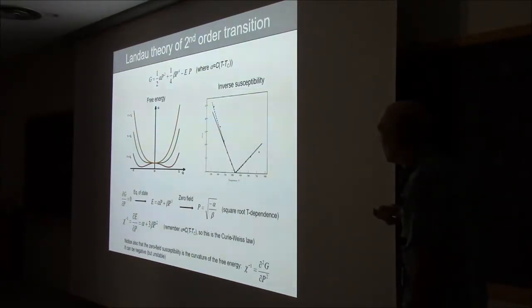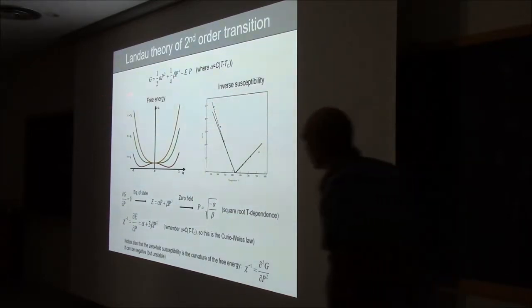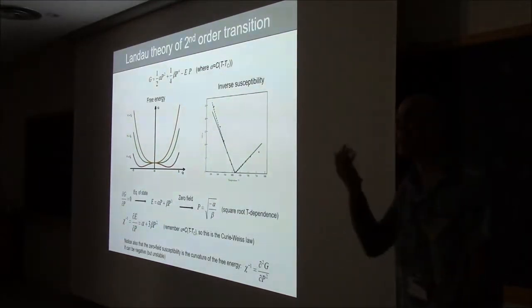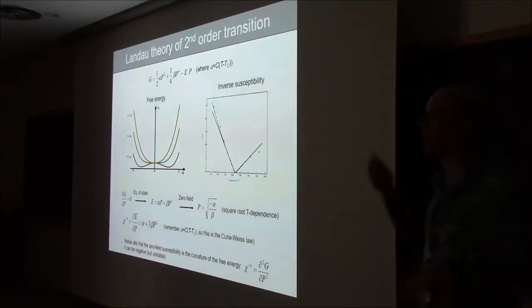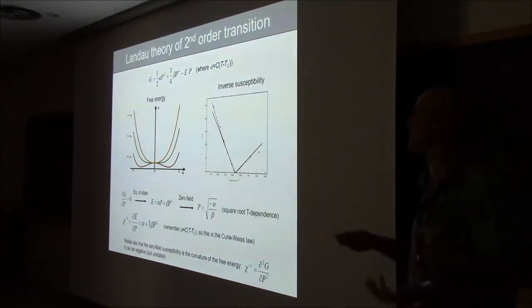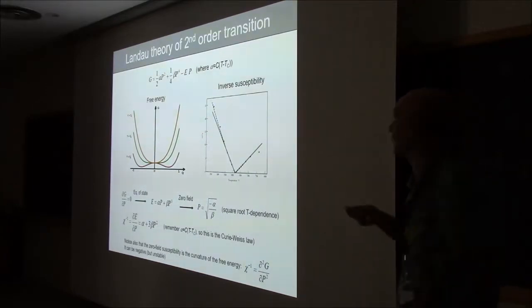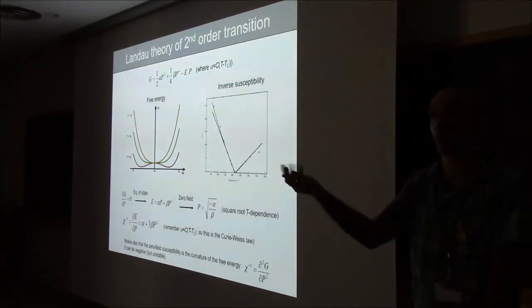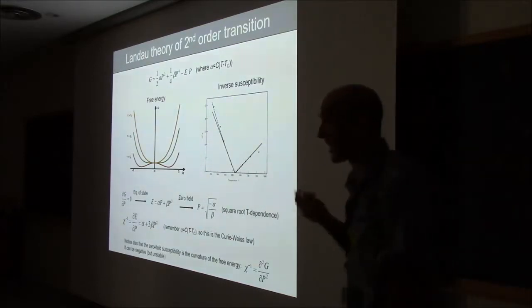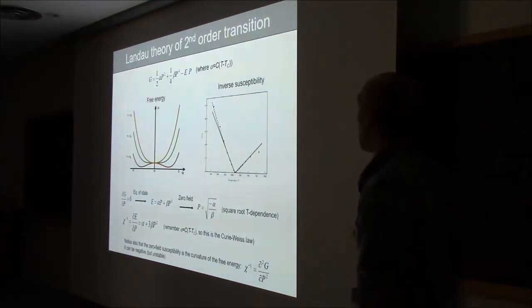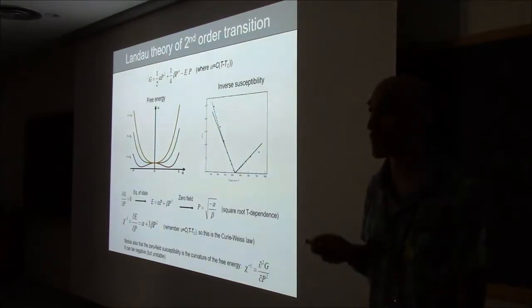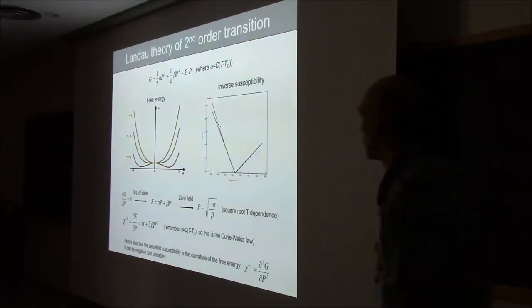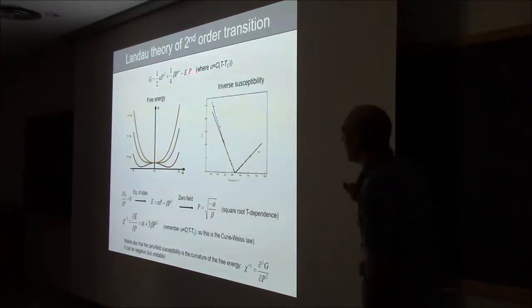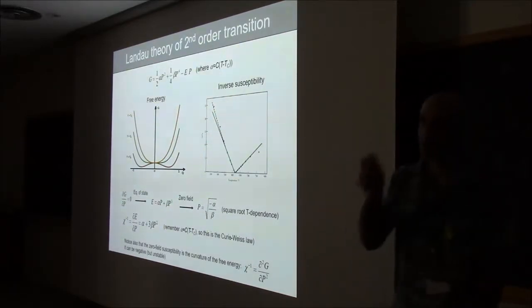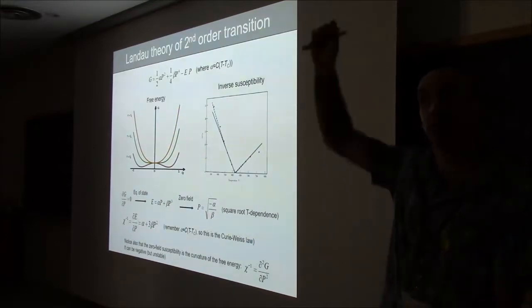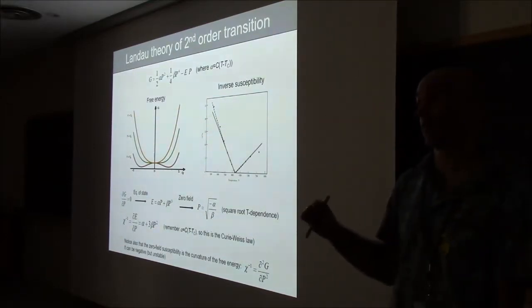Okay, so the minimum that you need to describe a phase transition. Landau theory starts with a thermodynamic potential that describes the energy of your material as a function of the order parameter, which in a ferroelectric obviously is the polarization. It's essentially a Taylor expansion, and what you put in the Taylor expansion will determine the solution. This thermodynamic potential needs to be able to describe both the high symmetry phase and the low symmetry phase of your material.